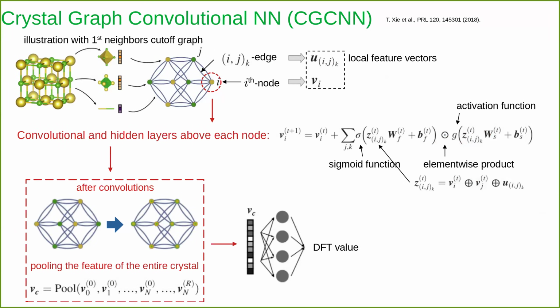We are using the CGCNN, the crystal graph convolutional neural network approach, which is actually two layers of neural network. First, you take a crystal structure, and this crystal structure is coded into a descriptor vector with the help of some convolutional layers, and that's explained in this slide. I think some of you might be familiar with this, but I did a short intro. If, for example, you take only the first neighbor cutoff distance to build a local environment, then you have such an octahedra along each FCC lattice point here, and then you can build such a graph.